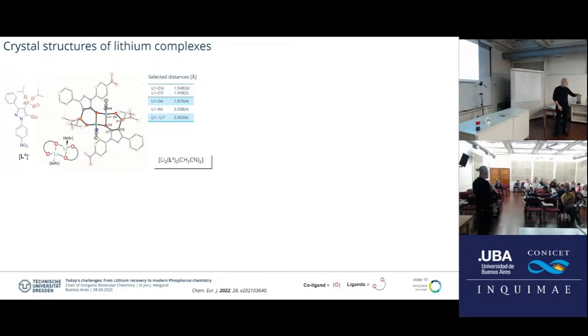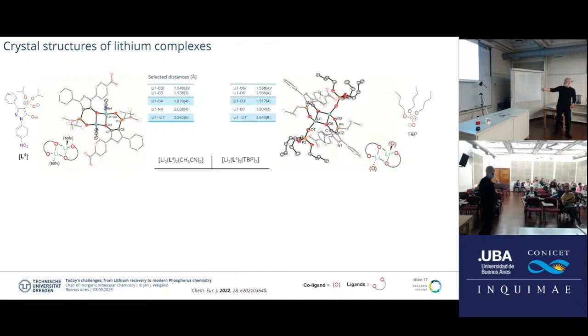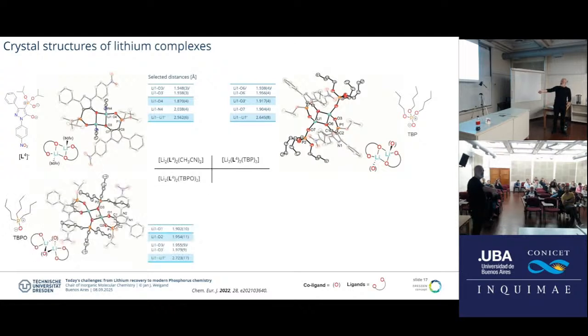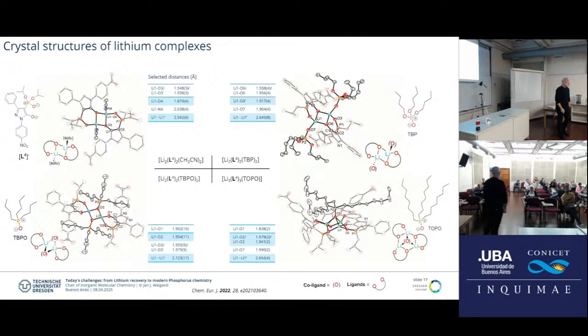And so what we also needed to do most of the time in the extraction studies is to have a co-ligand. And we also could see that the co-ligand is quite influential in the coordination of these corresponding cations or lithium together. So we have a dimer, a different kind of dimer with solvent, with a co-ligand. This is like a phosphorus ester, very typically used in extraction studies. We even have a combination of both, and we even have a trimeric, trinuclear compound, which again is here phosphine oxide on top of it, which also coordinates. So I think it's one of the first crystal structures where you see the corresponding extractive species, which you can then extract out of the aqueous phase into the organic phase to separate from potassium and from sodium.